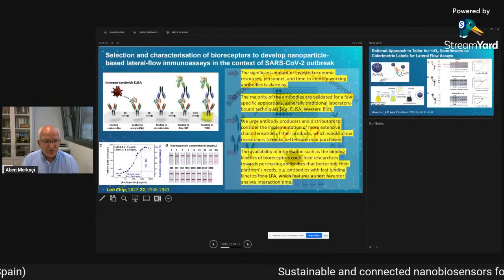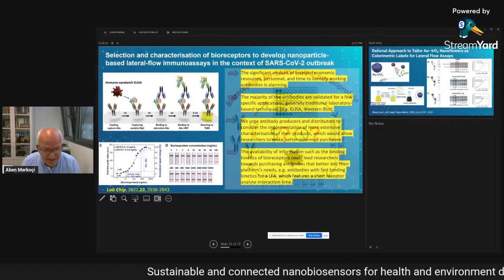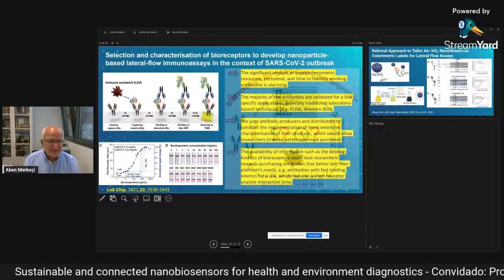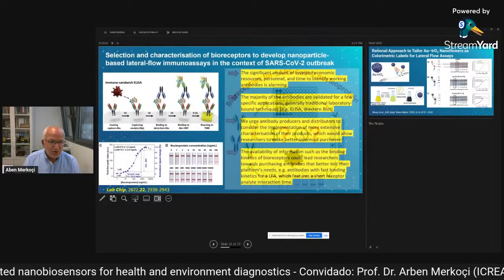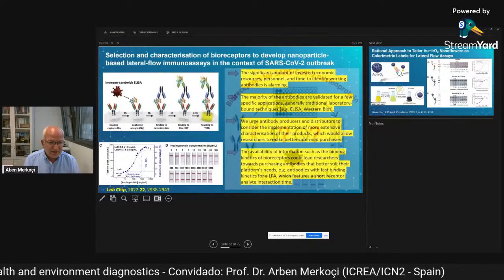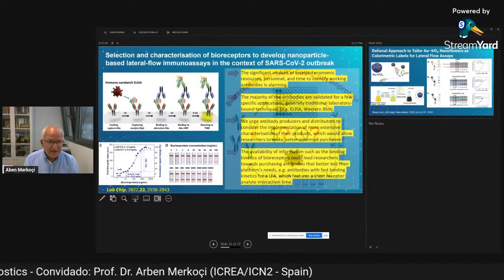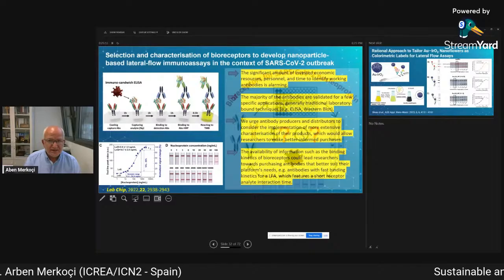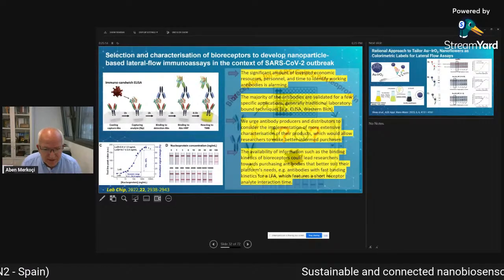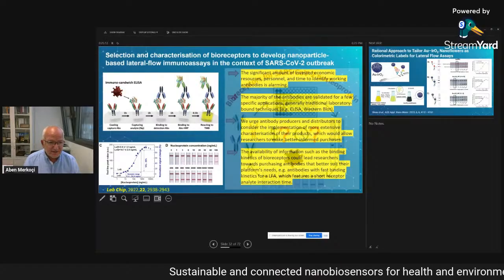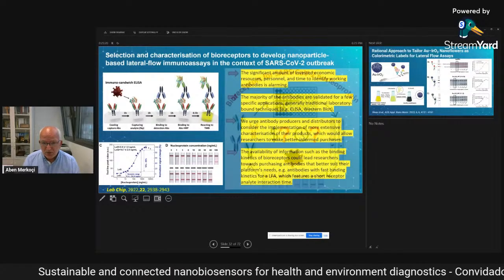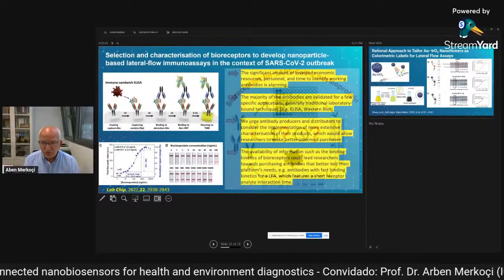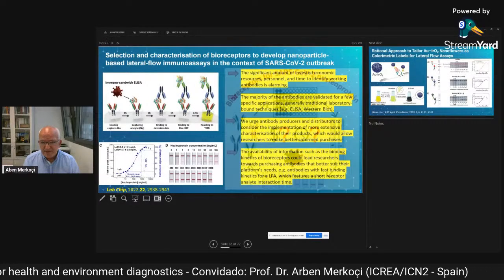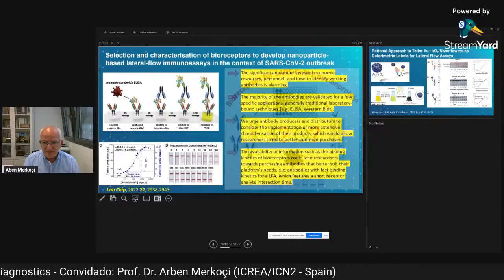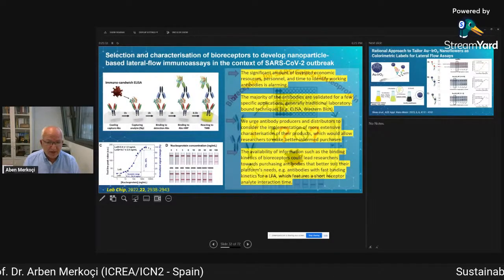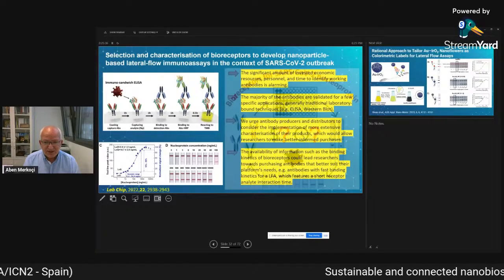We have been working with this also during COVID, and one of the very interesting findings is related to how you bind the system, how you develop your lateral flow, and one of the main issues is to define the affinity of antibodies against, in this case, SARS-CoV-2 related protein, and we found that some of the antibodies that were in the market were not with the right affinity. So it is very, very important to validate first these biomarkers, usually using ELISA, Western blot, but also it's very, very important before using these and setting up the device to have data about this.